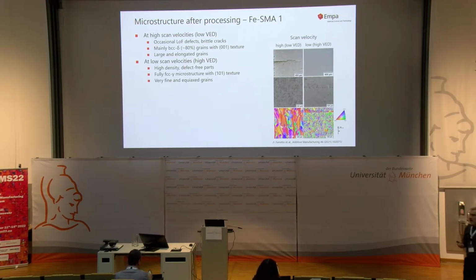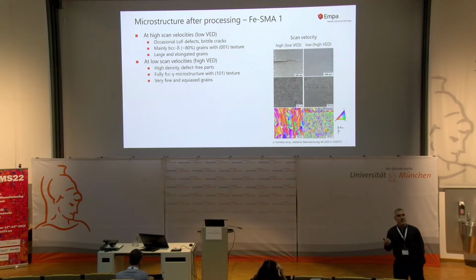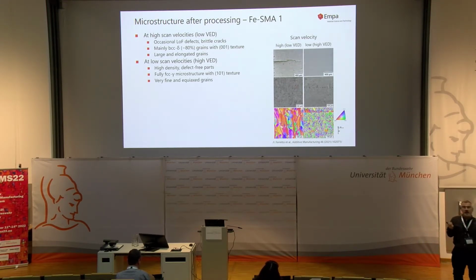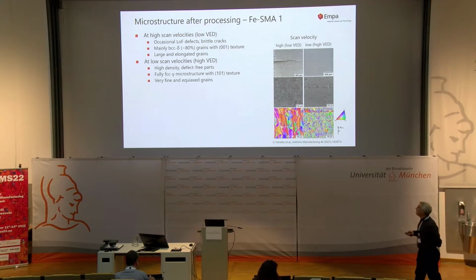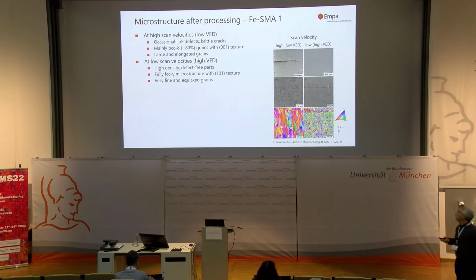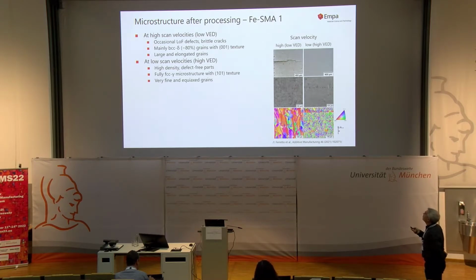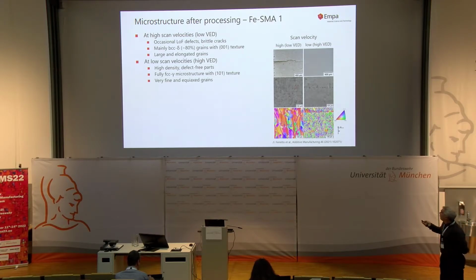Having a look into the microstructure, we already found some interesting things. So first of all, it was fairly easy to print them with regard to porosity. So we have a wide range where we can really fabricate dense parts. But roughly, with the tendency, if we go to high scan velocities, so low volumetric energy densities, we saw occasional lack of fusion defects and very often these brittle cracks. With regard to the phases, we saw that we have a lot of BCC delta in the material with a very pronounced texture, and we have these very large and elongated grains as we know them from additive manufacturing.